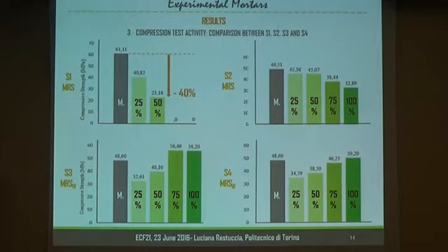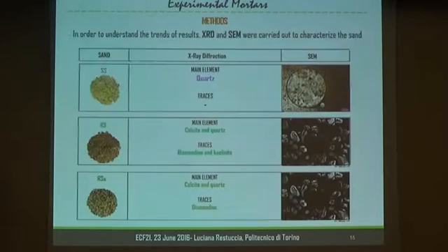The compression test activity follows the trend that we obtained in the TPB test. As you can see, in series 1 we had a huge decrease in terms of compressive strength, while in series 2, series 3, and series 4, we obtain more comparable values, related, obviously, to the quantity and the addition of superplasticizer during the mixing phase.